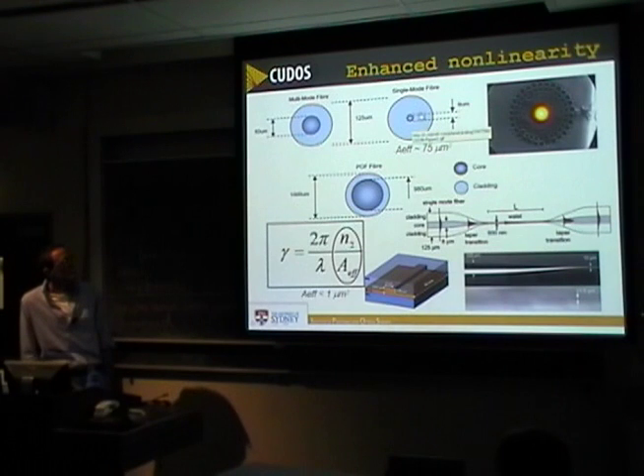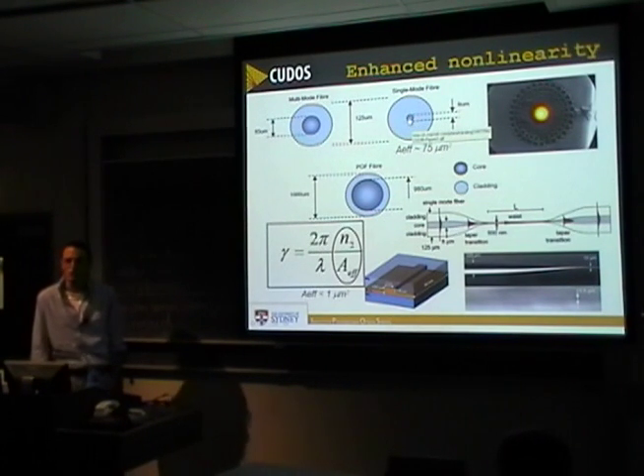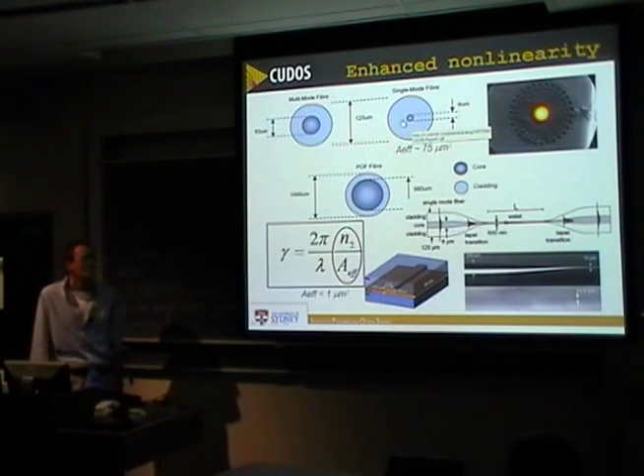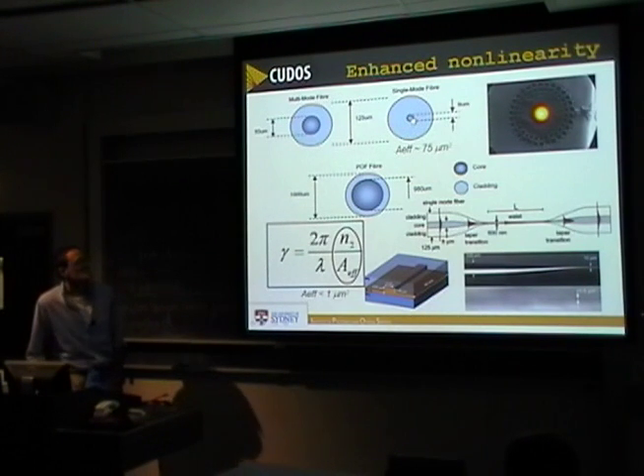In silica fibers, there's not much index contrast between the core and cladding. It's only a fraction of a percent. So we can't just arbitrarily make the core smaller and smaller to confine the light more and more, because the field will just spread out. There's not enough index contrast to really tightly confine that mode in this smaller core.